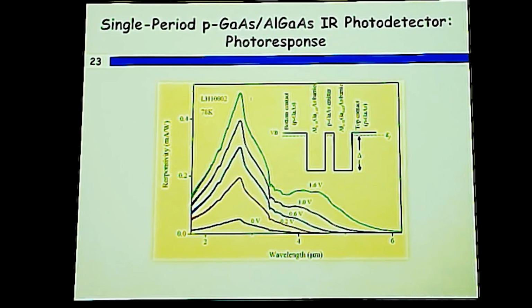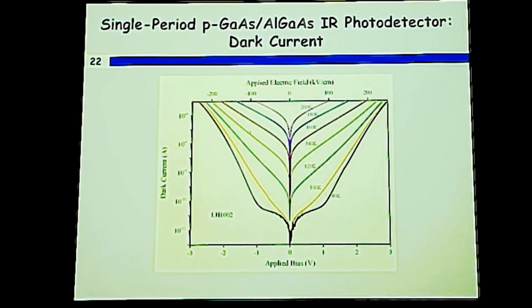So Dilip, can you explain the dark current? Sure. So what we do is we mount the sample in a cold finger, which is enclosed by a metal shroud. So it is completely isolated from radiation from the external environment, and that is cooled down to low temperature. And we measure the current. We apply bias and measure the current, like in a resistor. But the property of this is semiconductor. It is not just like a metal or other regular resistor. The resistance is dynamic. It changes with the bias applied. But in principle, it is like measuring the current in a resistor.